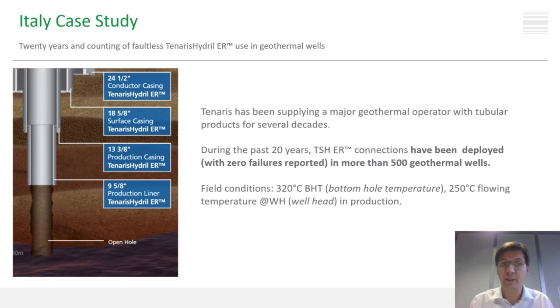The first case study that we present is related to a long-term relation that we had with a major geothermal operator in Italy. This operator has been exploiting geothermal reservoirs with high enthalpy, with 320 degrees C bottom hole temperature, typically 250 degrees C of flowing temperature, and mainly producing steam for power generation. During the past 20 years, Tenaris ER, Easy Running Connection, have been used basically on all the sizes, going from 2 7/8 to 7-inch liners. No failure has been reported, and the connection has been used in more than 500 geothermal wells.